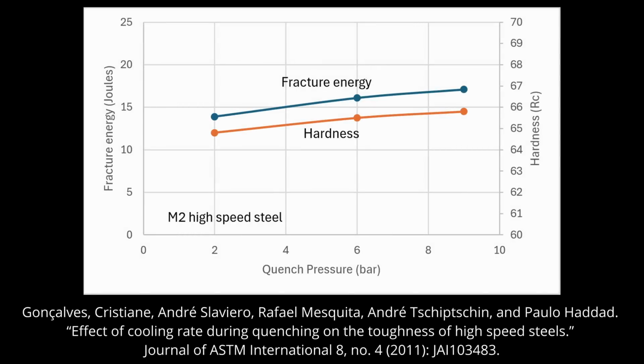Slower quenching means that the hardness and toughness is reduced. So here I have a published study on M2 high-speed steel where they tested with a 2-bar, 6-bar, and 9-bar quench in a vacuum furnace. They tested the hardness, and they also tested the toughness with a bend fracture test. With higher quench pressure, both properties were improved.